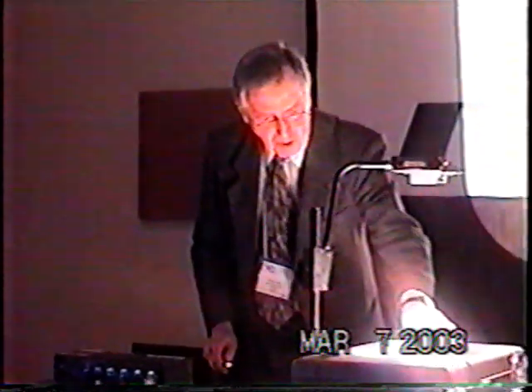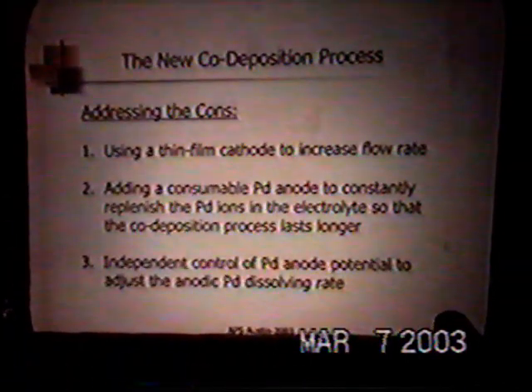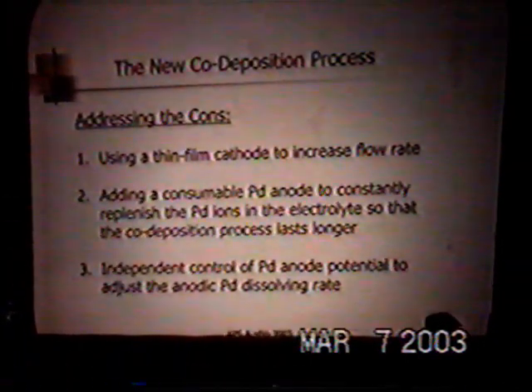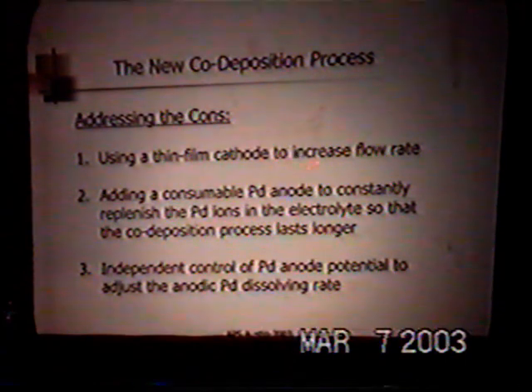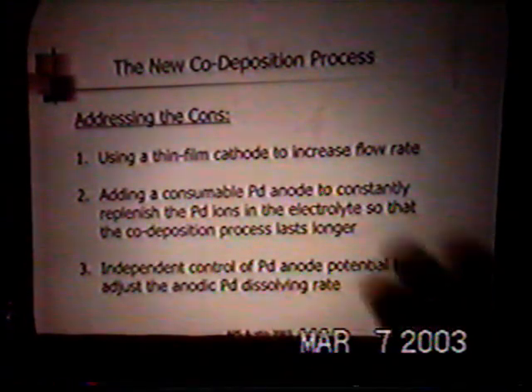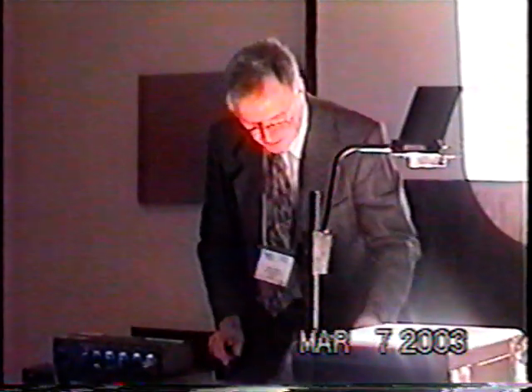So we've looked at this alternate process, which would attempt to get around that, and have used a thin film cathode as a substrate essentially to increase the flow rate, and have a consumable anode that allows you to continuously replenish the palladium. And so the setup is like so.